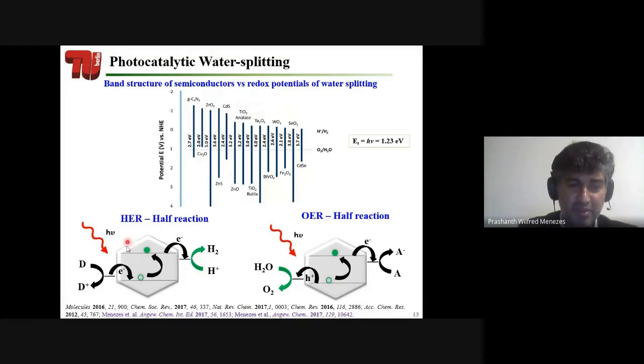So this is the same semiconductor that I showed you in the previous slide. You have an incident ray from your light, and then you hop your electron from your valence band to the conduction band. What you immediately do, you quench the hole. You introduce a donor molecule which donates the electrons to the holes. So the holes are filled, or quenched, and the electrons are available here, and you use those electrons to produce hydrogen.